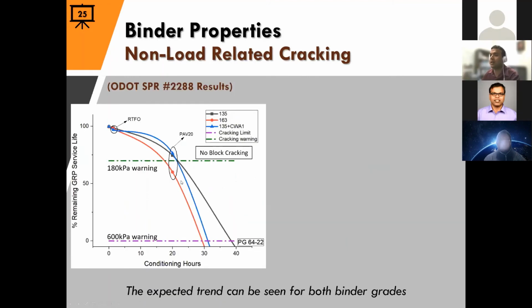So we have done similar work. This is our PG 64-22 material, and there is a chemical warm mix additive number 1. Intentionally, the name has been removed. But if you look at it, with the reduced RTFO temperature of 135, it takes almost 40 hours, like 2 PAV cycles, to actually go to the 600 kPa warning. In other words, the deterioration of the Glover-Rowe parameter, which is non-load related cracking performance, is slower when you short-term age at a lower temperature.